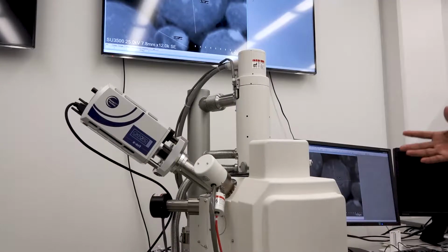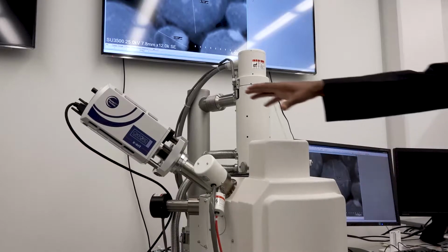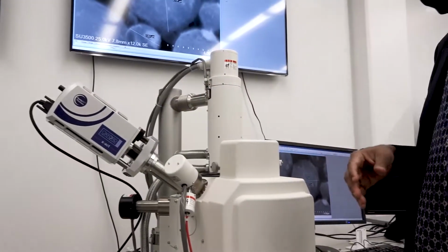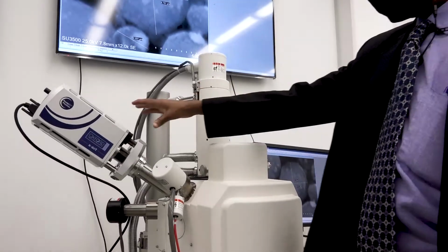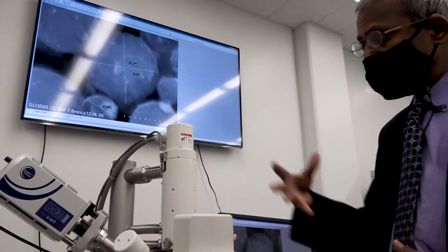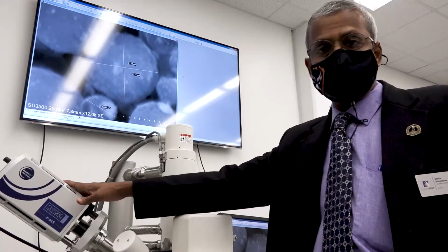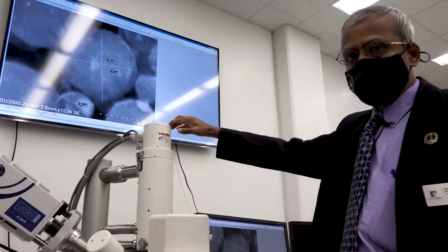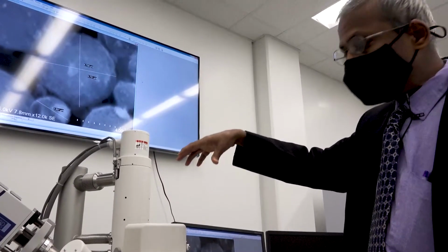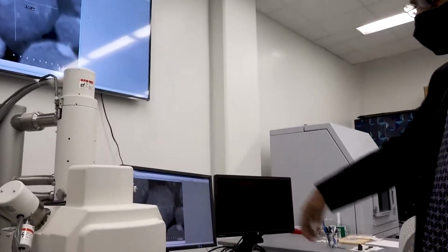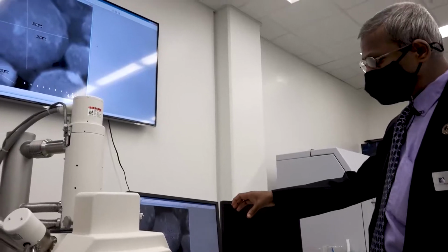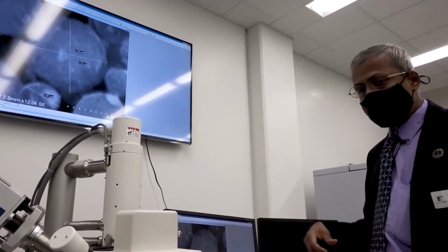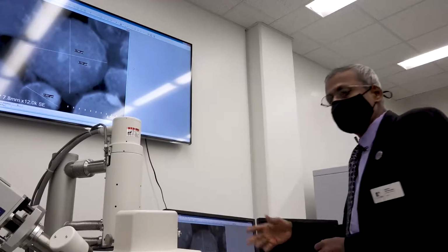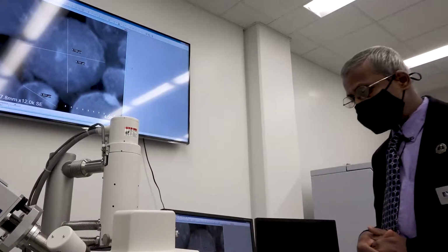Here, what you see is a scanning electron microscope. This is a very high-end tool from Hitachi, the SU3500. It has a detector called an EDS detector, which will give you the chemical composition of any material. For example, if we take a thermochromic material, it gives the concentration of elements like carbon, oxygen, and many others. There is an electron gun which can shoot up to 25 kilovolts and will image your sample. What you see on the monitor is a thermochromic nanoparticle, where you see dimensions of about 5.73 micrometers, which you can see on the monitor as well as on the wall.